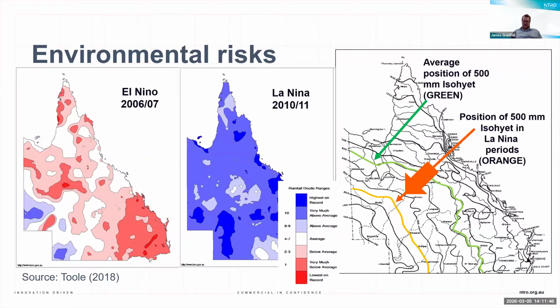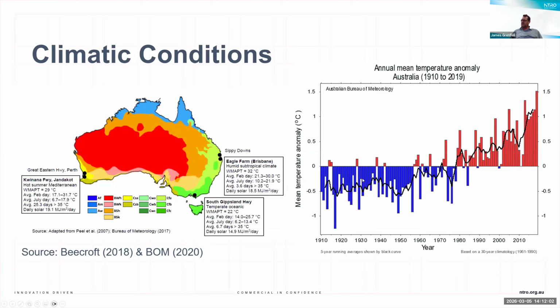Obviously, the higher temperatures affecting bituminous surfacings, asphalt, etc., very wet conditions, really affecting the unbound granular materials below, and especially the unsealed road network. And again, obviously, as mentioned before, generally Australia is very hot. And mean temperatures are only rising over time, significantly higher in the last 30 or 40 years, where average temperatures are continuing to go up, and understanding how to manage a network under those conditions is obviously a continuing problem.